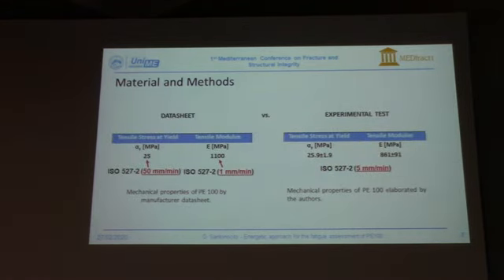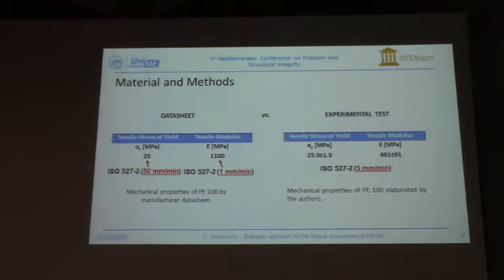Here we can see the different values of the mechanical properties of this material. These are the values from the manufacturer's data sheet. Essentially, the manufacturer adopts different test speeds in order to determine the mechanical properties. So we have a high speed for assessing the yield stress and a very low speed for the tensile modulus. So this kind of material, as we can see in the properties obtained by the authors, is extremely dependent on the applied velocity.